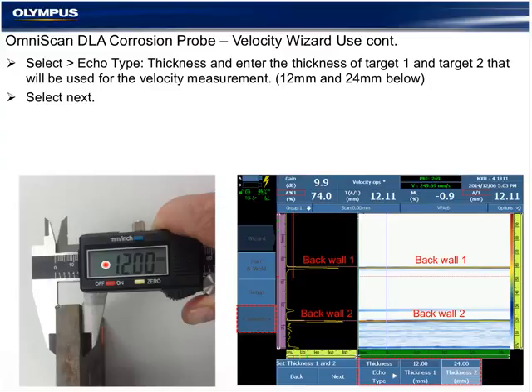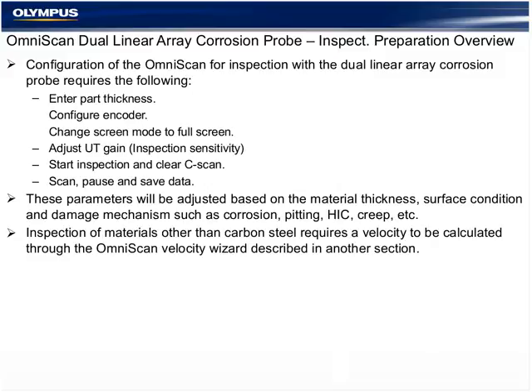That is the only way to get a new velocity other than carbon steel into the default setup files that come with the probe. Once the wizard steps are done with the new velocity, it adjusts the scale, it adjusts the UT axes, and the readings are then in tolerance with the new velocity. And again, there's a separate section within the presentation material you'll receive on each of the sensitivity, wedge delay, and velocity measurements, but keep it very simple. Under normal conditions, we would look at the step wedge, check it, do a dynamic scan, save it, and move on